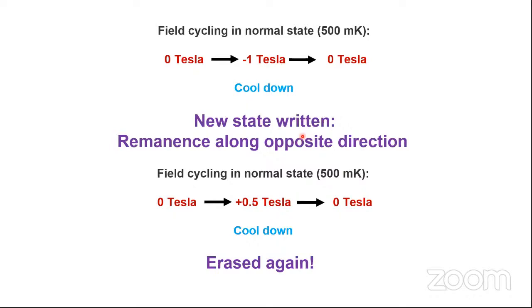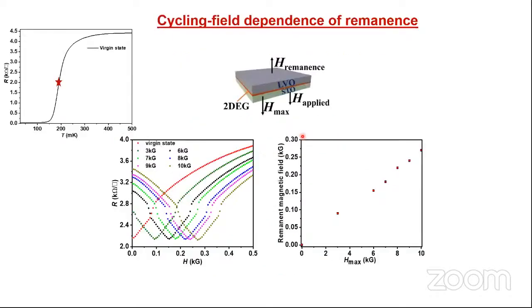So if it is appearing only at the interface, it may be very difficult to measure it by usual magnetometry. But in this case, the superconductor is helping us detect the magnetic state that is written or erased in the normal state. Now, is it something special about 1 Tesla?